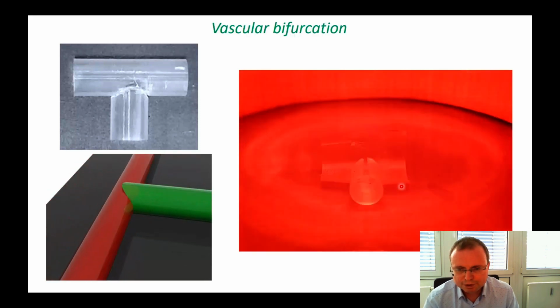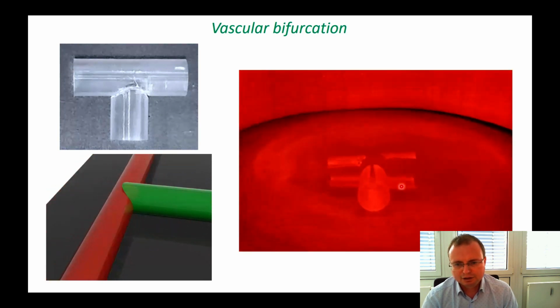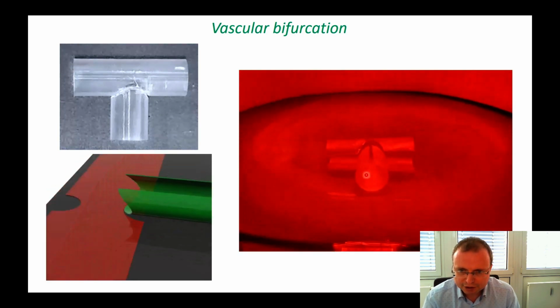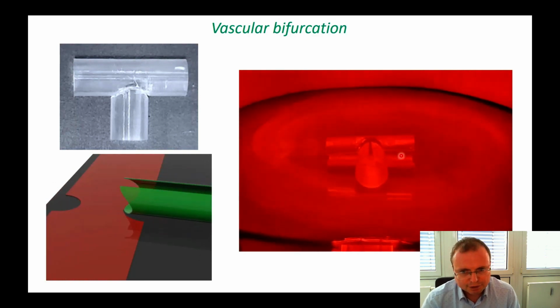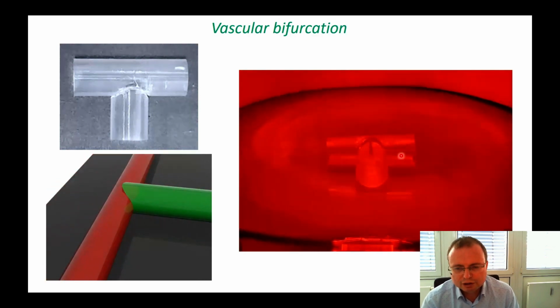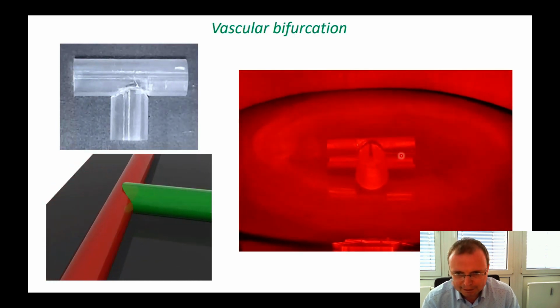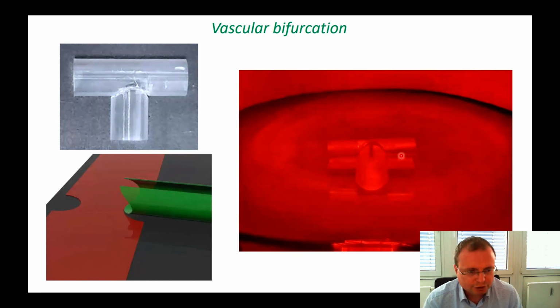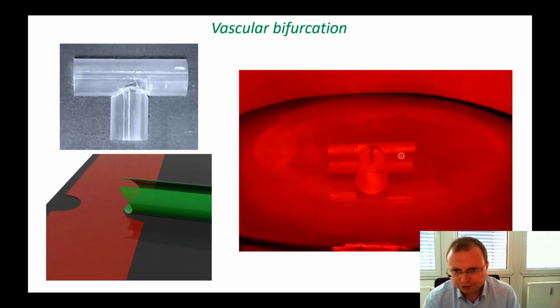Because these two pieces contained a certain amount of photosensitive particles, and this object contained more of them, and this object contained less of them. So in this particular case, we are able to coordinate the folding of two objects in time to allow for fabrication of very complex three-dimensional objects which cannot otherwise be fabricated using a single object.